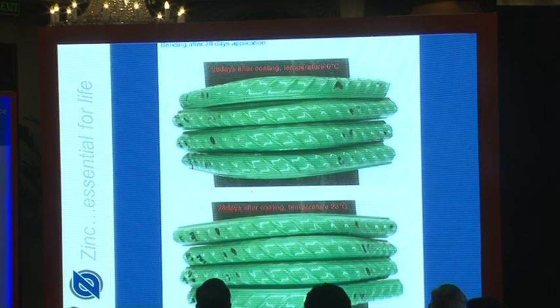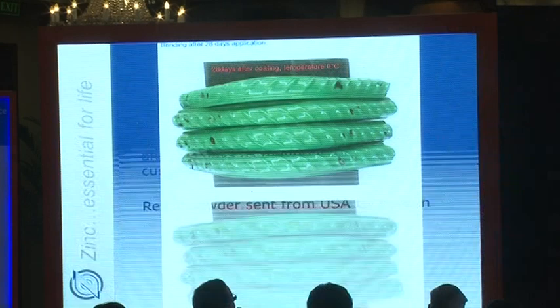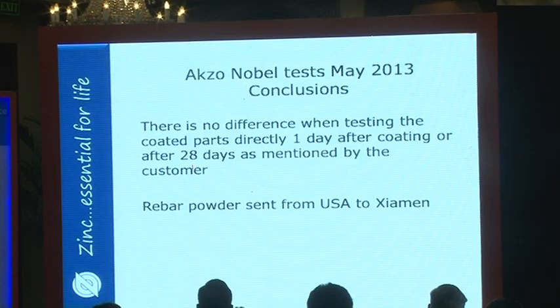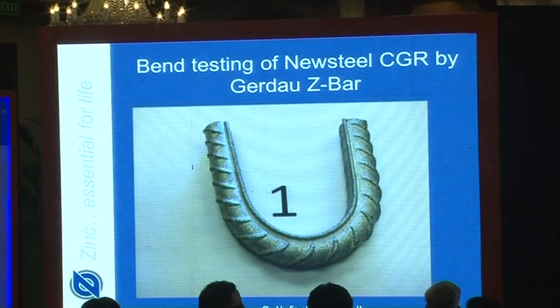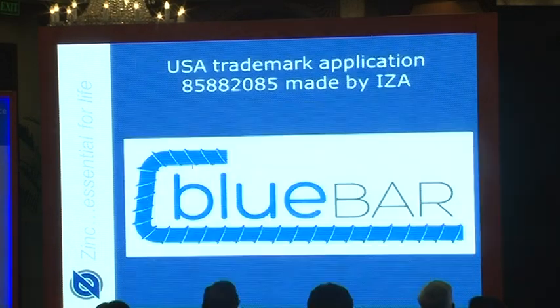We went out to 28 days because with epoxy you have this aging effect. It absorbs water, and we also see that we didn't have any cracking either at 0 or 23 degrees after 28 days. So we're very satisfied that we have an answer for the epoxy-coated rebar on top of the zinc coating. So we didn't see any problems with these, and that powder has since been shipped from the USA to Xiamen. It's the same epoxy powder that's used for coating the black bar in the USA. So there's no change there. Gerdau has also looked at this. They found no cracking on the bends.